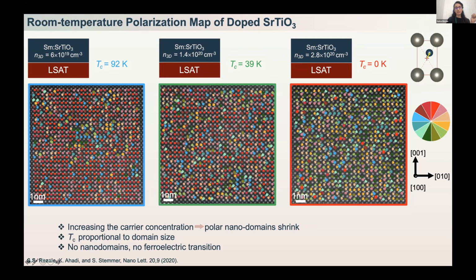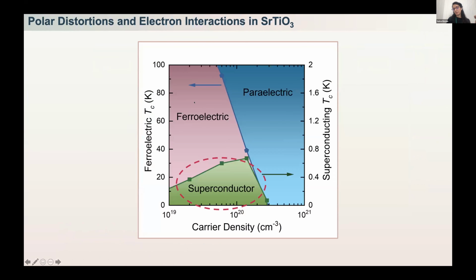So here you can see that by increasing the carrier concentration, these polar domains are shrinking in size, and that is very aligned with the ferroelectric transition getting suppressed. And you can see that if we don't have any domains, we won't have any ferroelectric transition happening at the lower temperature. So that clearly explains the ferroelectric part of this phase diagram: when we increase the carrier density, the ferroelectric transition is getting suppressed because the domains are not forming anymore, because of the introduction of these dopant elements in the structure.